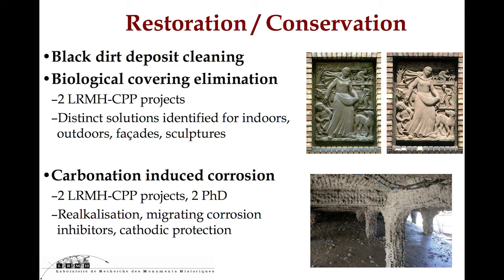For the restoration and conservation tools, we performed two national projects on black dirt deposit cleaning and biological covering elimination, and we identified distinct solutions for indoors, outdoors, facade, and sculptures. And we realized a technical book with all the recommendations. So concerning the carbonation-induced corrosion, we performed projects on realkalization, migrating corrosion inhibitor, and cathodic protection.